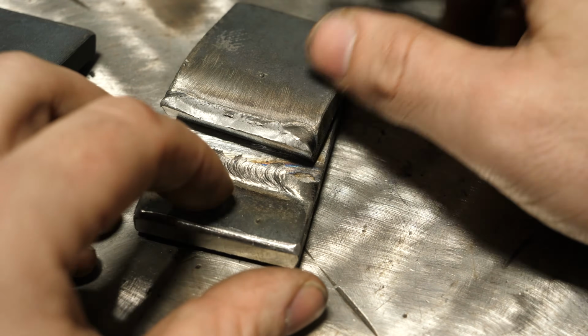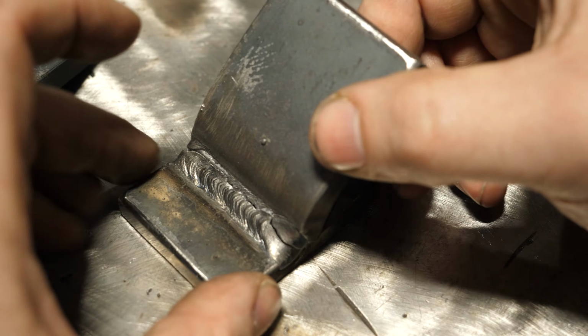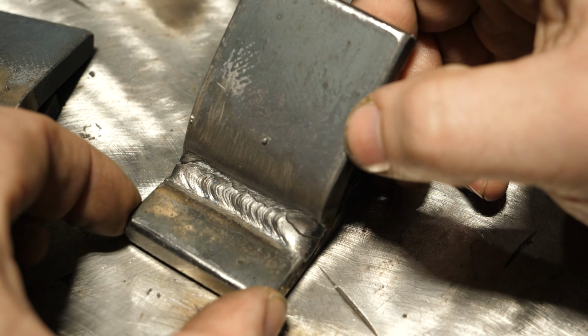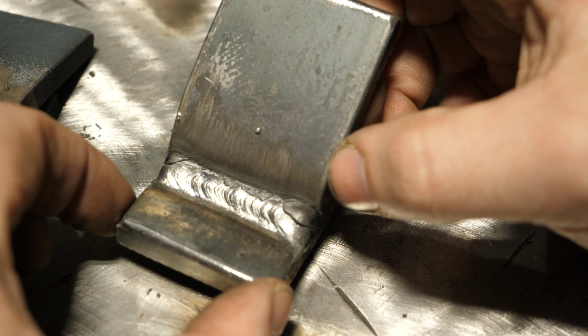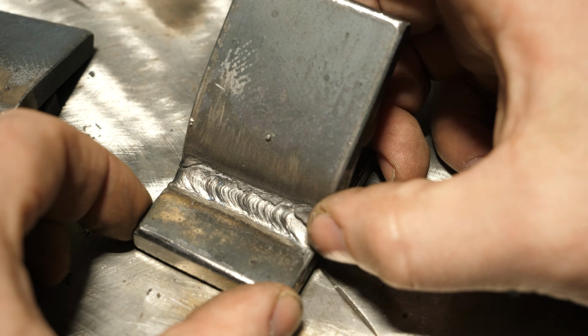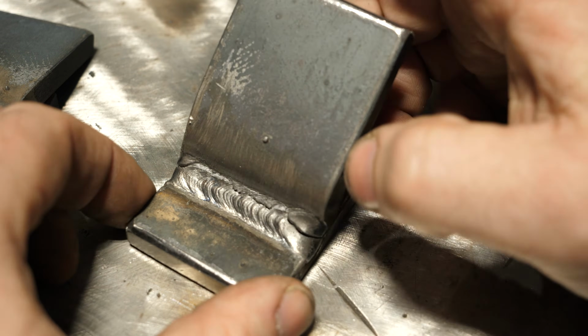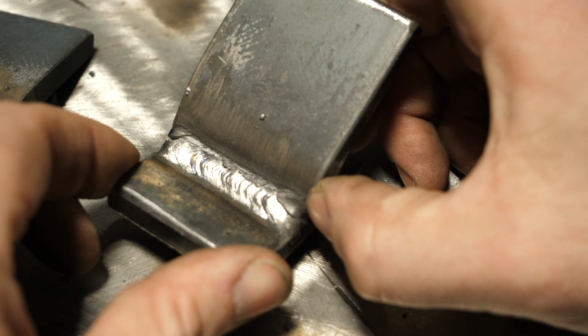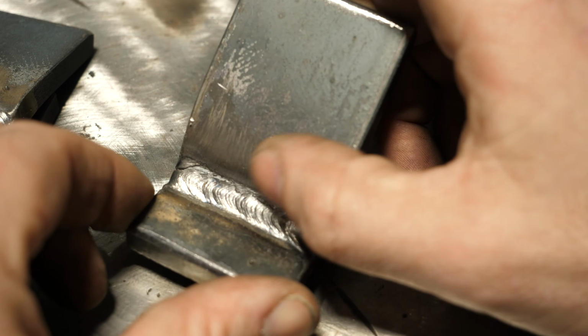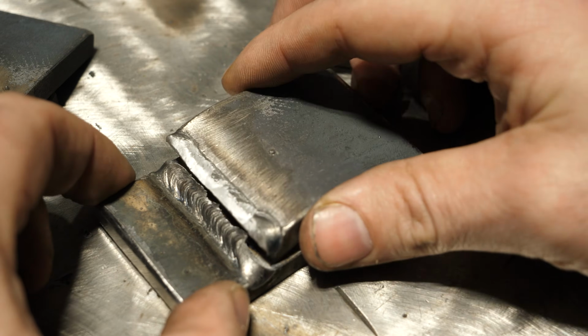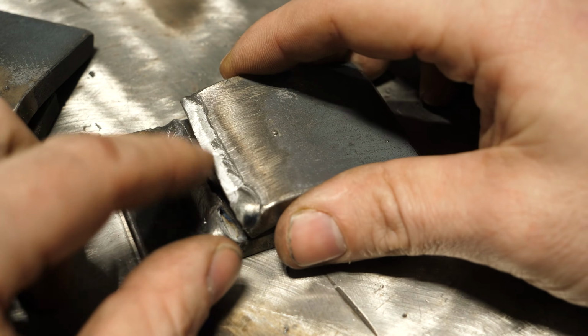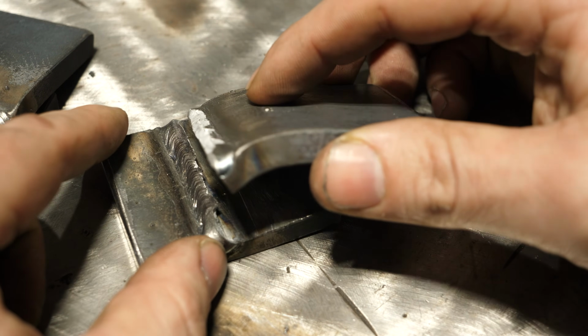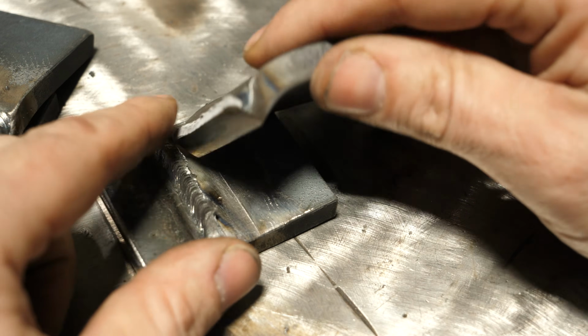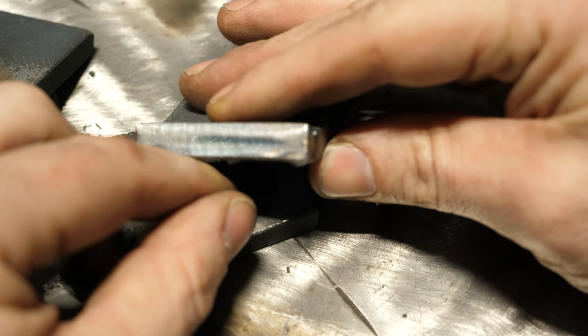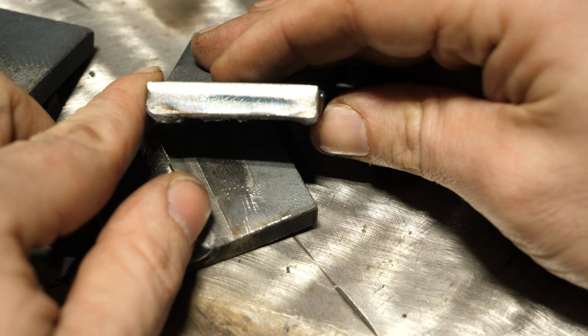This one is far more interesting. I looked over this pretty closely, and this is basically more or less about as good as you can get on this without going back and restarting and filling this in. Again, the weld cracked over here a little bit and then propagated up. But when you actually look at this, the whole weld actually failed itself. When you look, there's no penetration there. Let me zoom in.